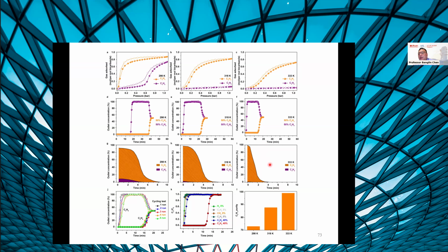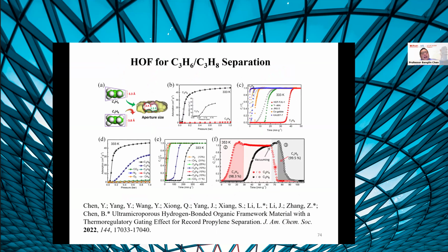Compared with MOF material, the good thing for HOF is we can easily recrystallize the organic compound. So we can reuse the organic compound again and again. That will significantly reduce the cost of the material for future application, because it's very, very difficult for us to recover the organic linker and recover MOF material. So this is a uniqueness. And also this material can even be utilized for the separation of propene and propane, and even the four components of ethylene, ethane, propene, and propane can be separated.